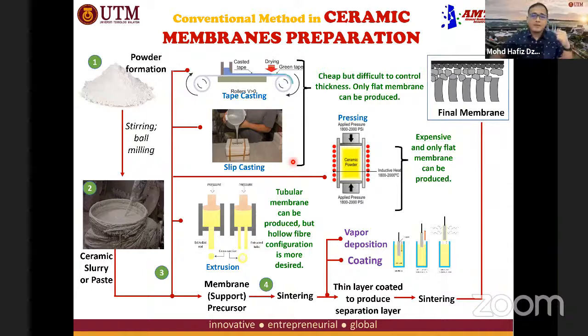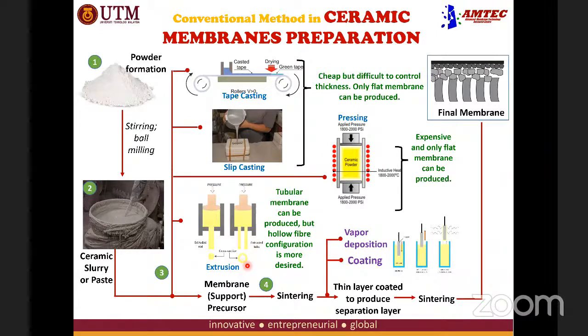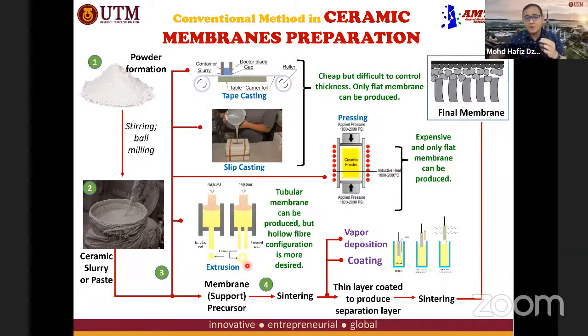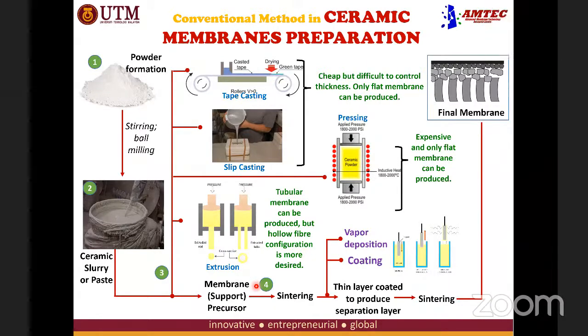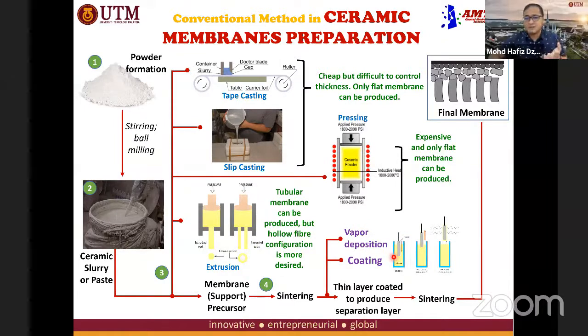Okay, and if we want to produce the tubular membrane, we have to use the extrusion process. Tubular means that it looks like a straw, and the size is normally from 5 centimeters up to 10 centimeters. Okay, so you have to do sintering after you get the precursor in order to turn it into a strong ceramic body, and after that, in order to alter the pore size of the membrane, we have to do a deposition technique. Either you can use vapor deposition or you can use coating, followed by one sintering.